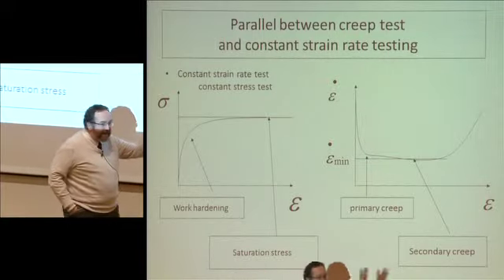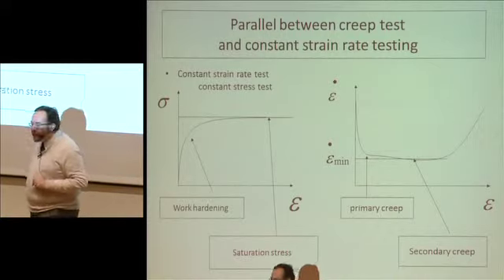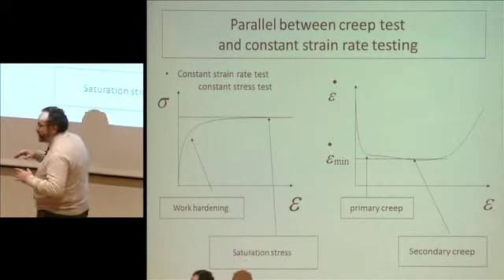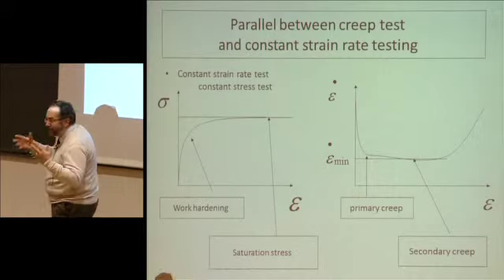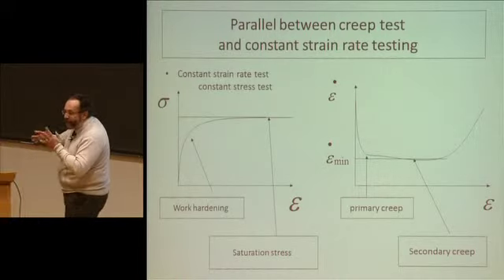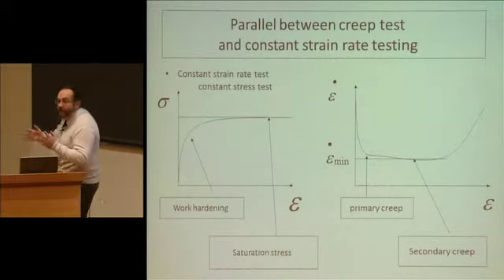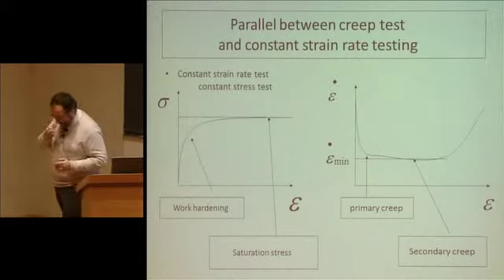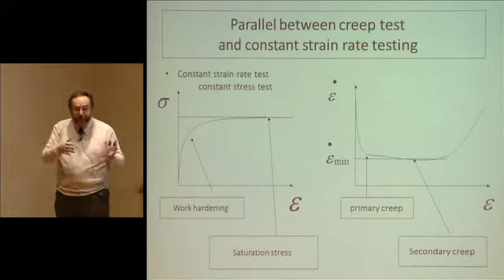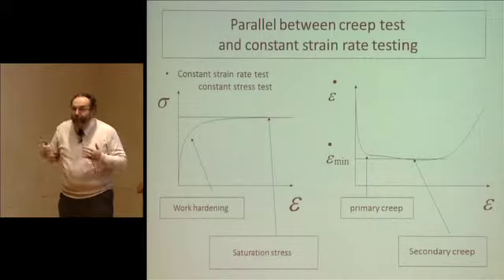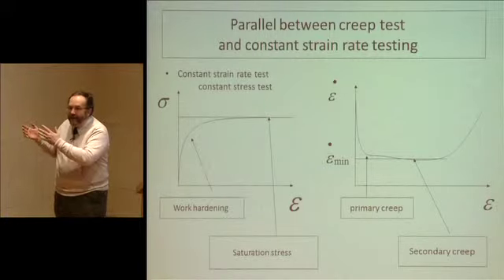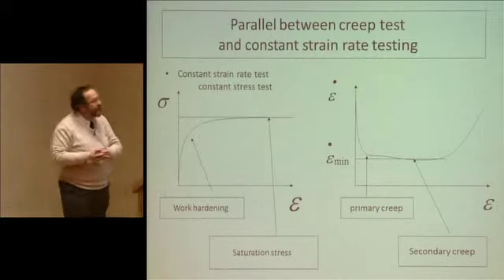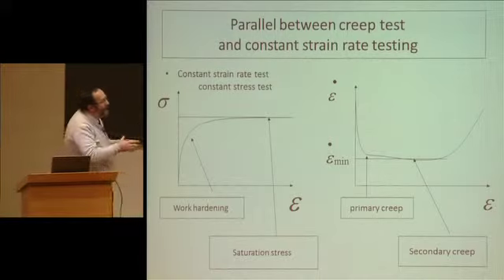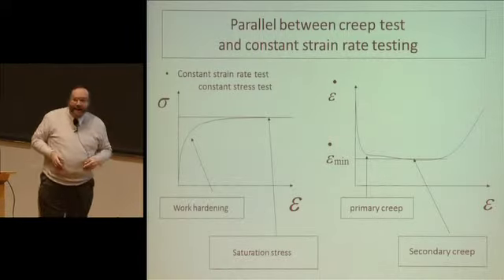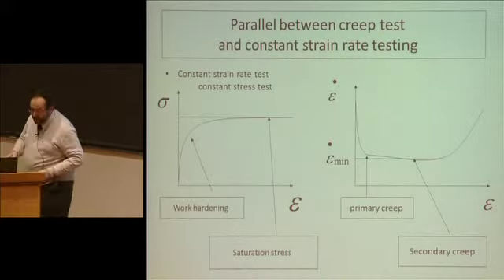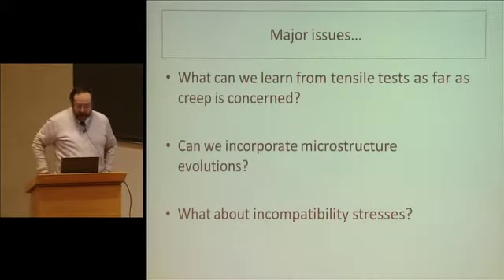You have a dislocation density that's essentially constant because of the balance between the stress you're creating and what you're annihilating. When you have more and more, they tend to annihilate each other more easily in pairs of dislocations, plus B minus B, and you have a dynamic balance with a defined speed that should describe the stationary condition, which is dynamic with imposed constraints.